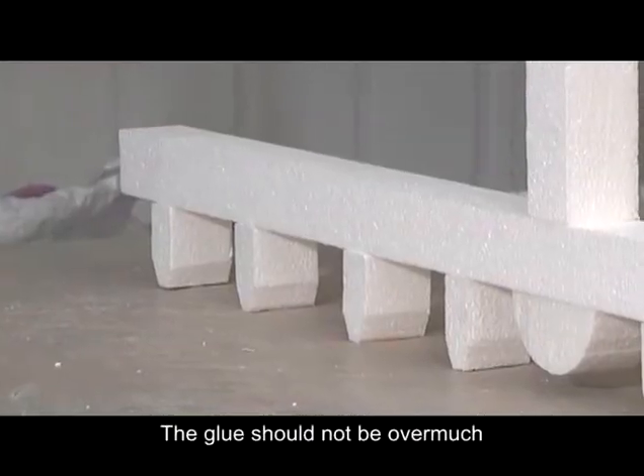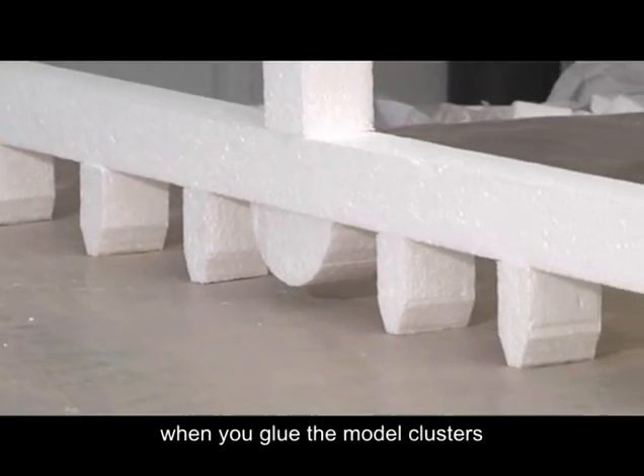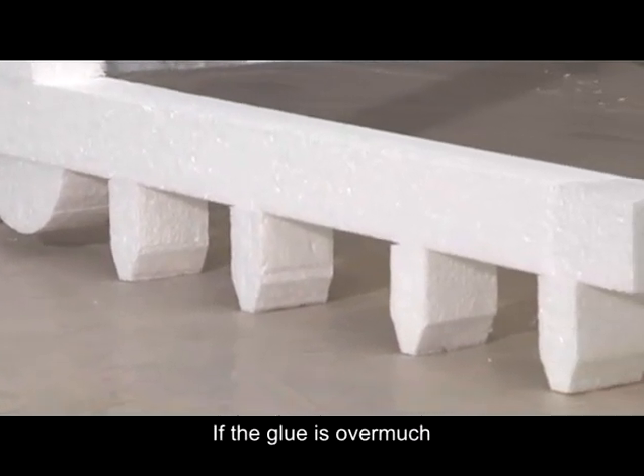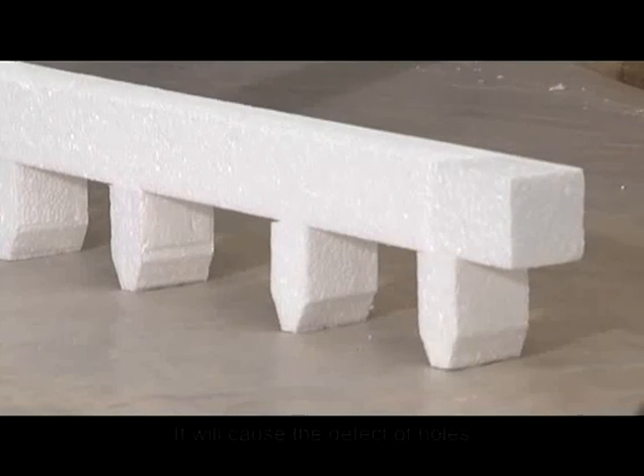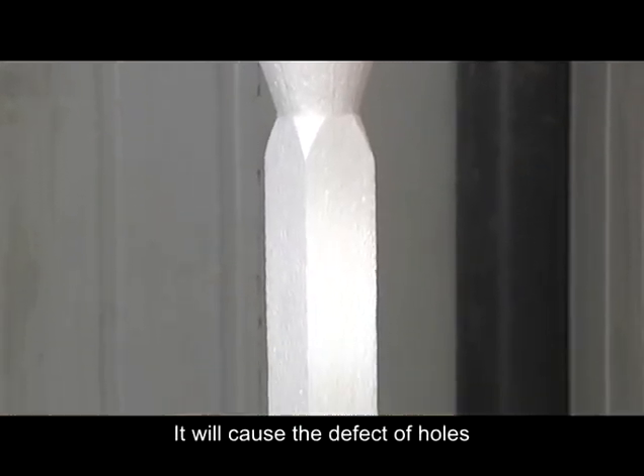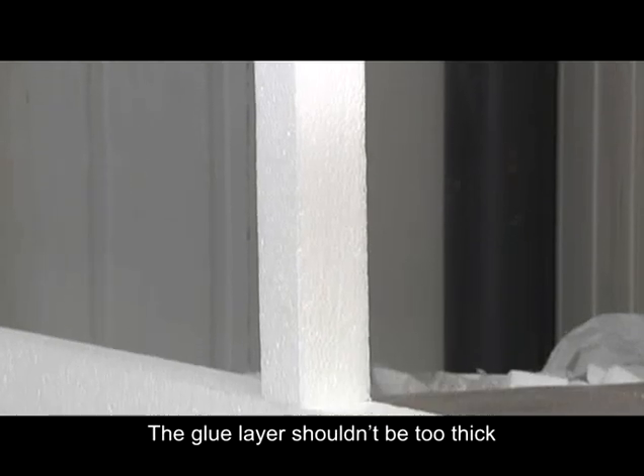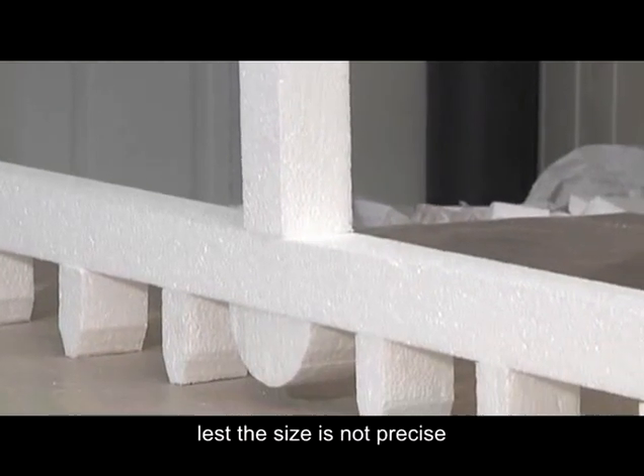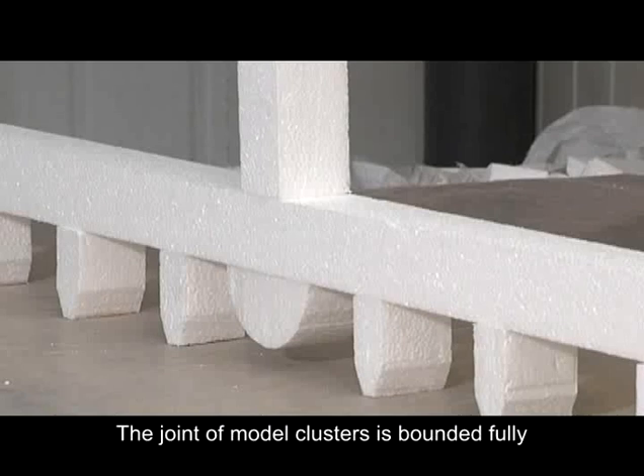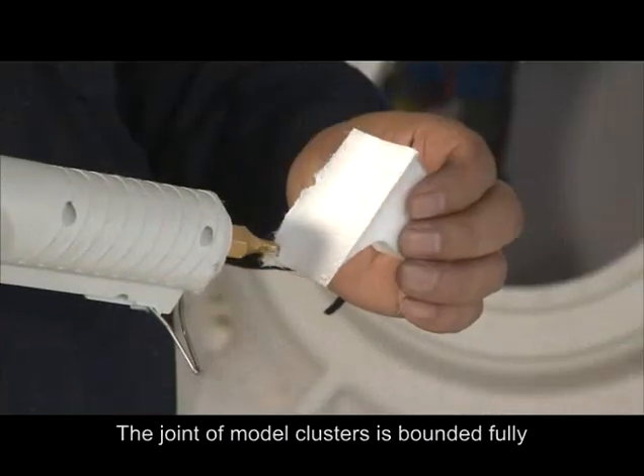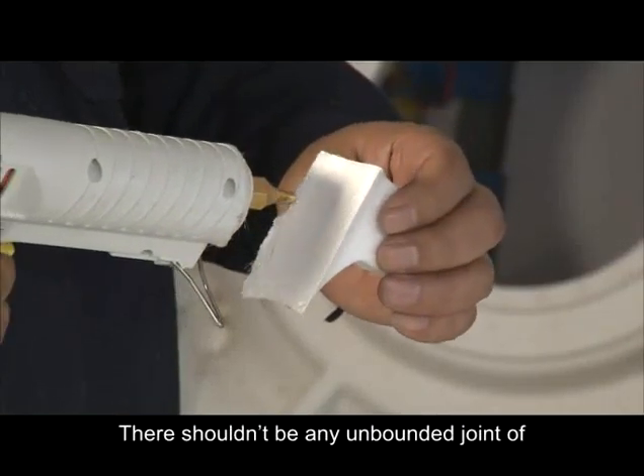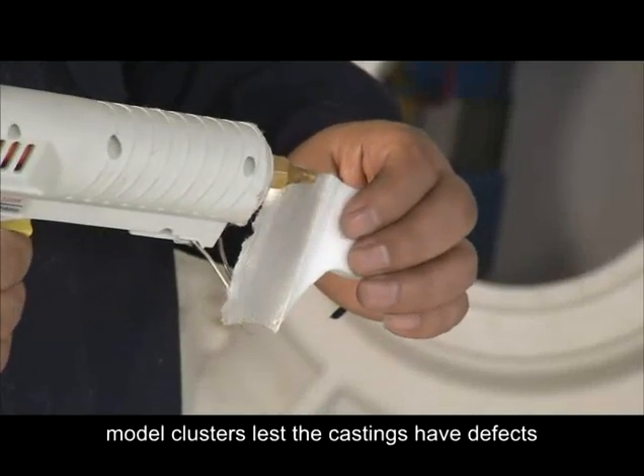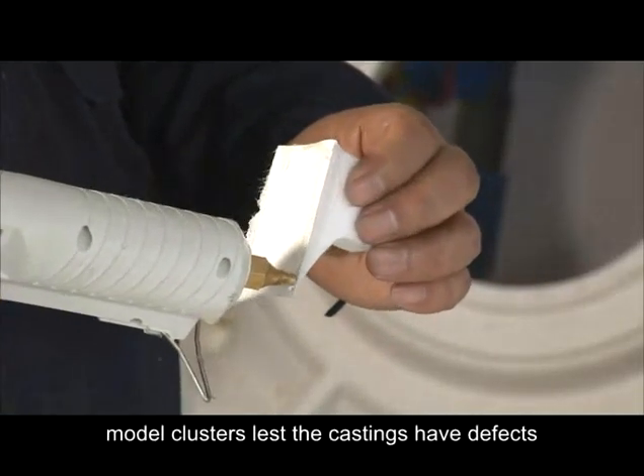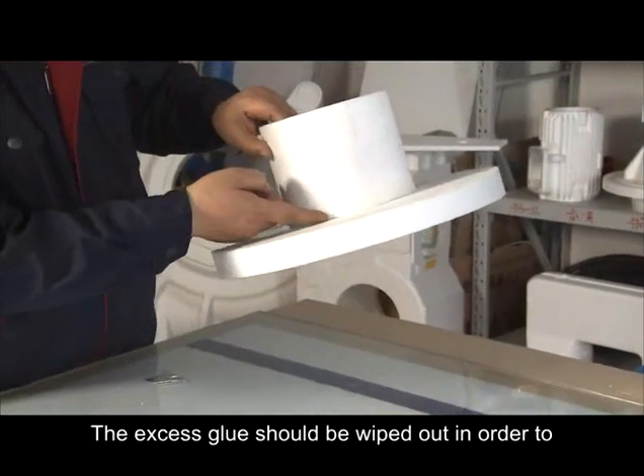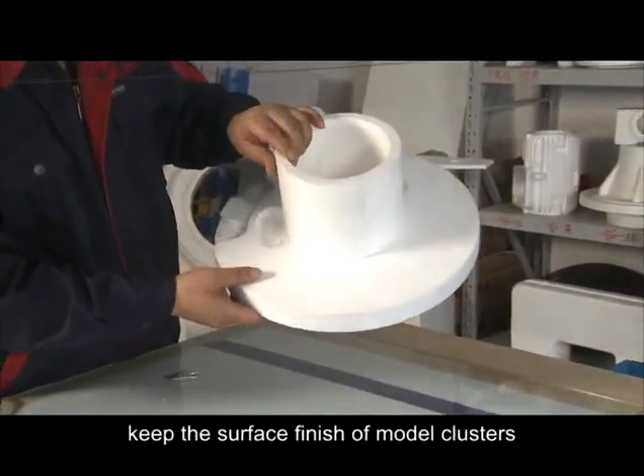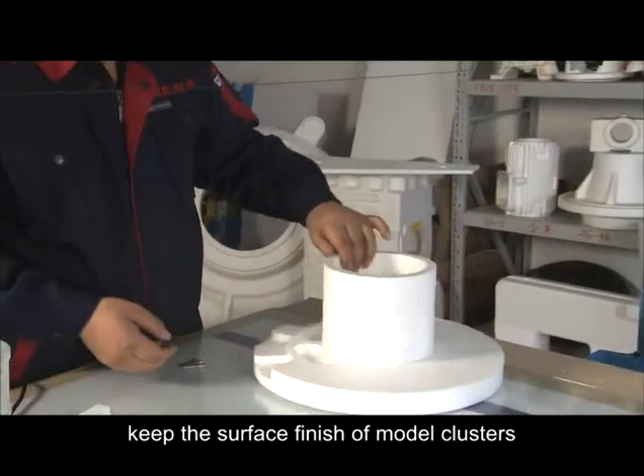The glue should not be overmuch when you glue the model clusters. If there is too much glue, more gas will be produced, which will cause hole defects. The glue layer shouldn't be too thick, lest the size is not precise. The joints of model clusters should be bonded fully. There shouldn't be any unbonded joint, lest the castings have defects. The excess glue should be wiped off, in order to keep the surface finish of the model clusters.